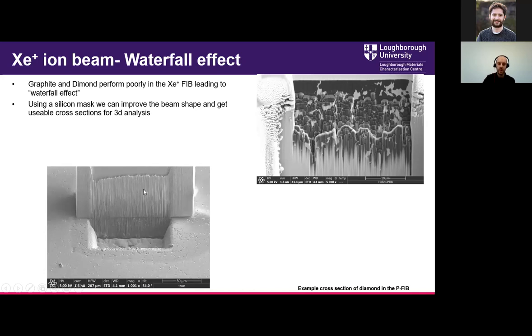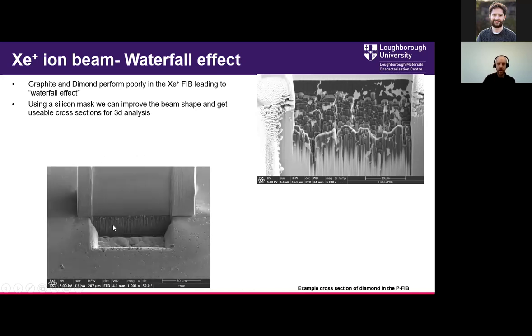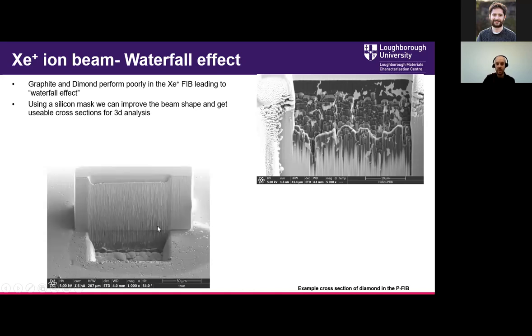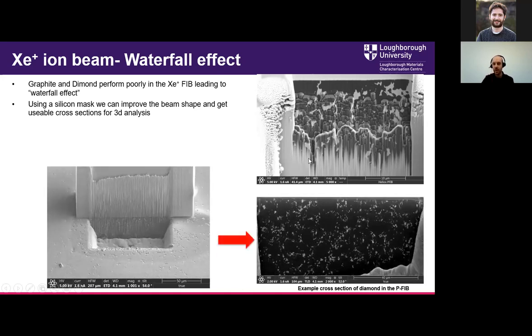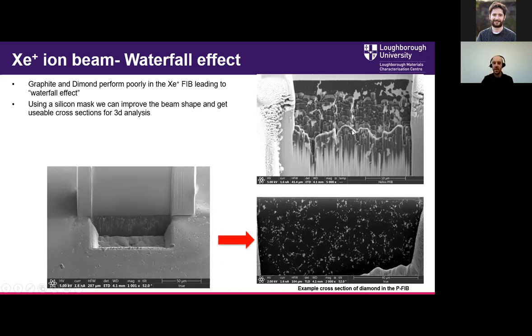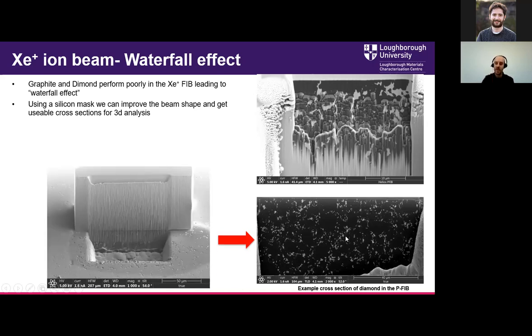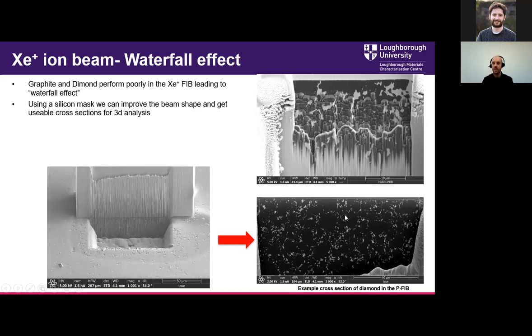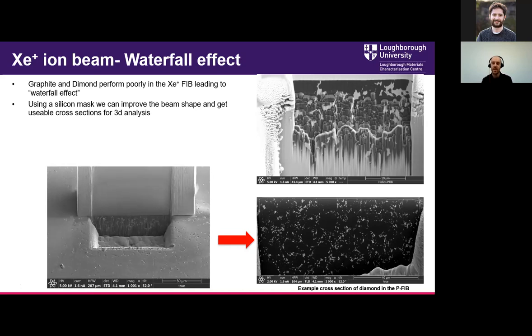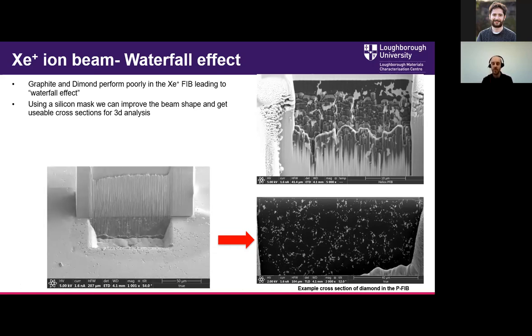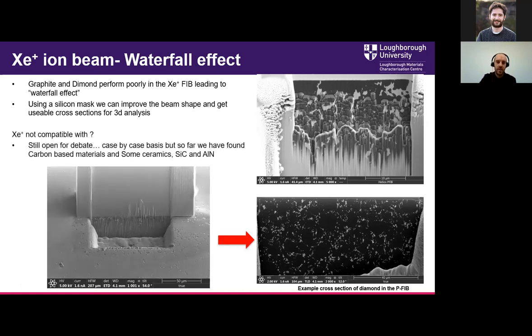So here on this little video, you can see the silicon mask. And as we cut through the silicon mask, the cross section of the diamond improves. And we go from this image in the top right, where we've just got this horrible waterfall effect, to again a more usable image where we can see the different phases within the diamond. We can see the diamond particles and also the cobalt binder phase.